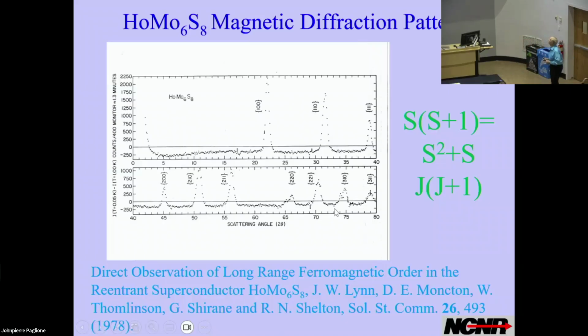And then you have a deficit of scattering everywhere else, because the scattering has shifted from everywhere up to there. So when you make a measurement, you measure the square of the ordered magnetic moment in the system. The other S part is all the inelastic scattering that's left.